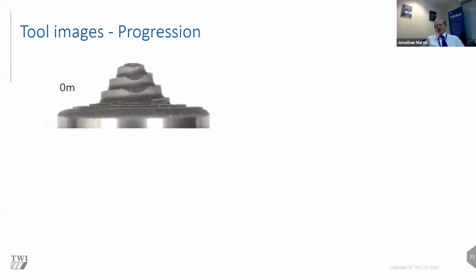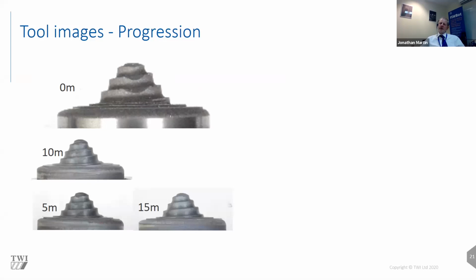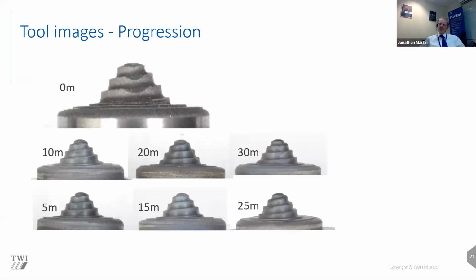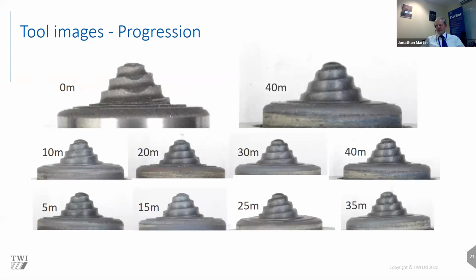So I did mention that every weld, we took a picture of the tool. So this next slide is really showing that progression as the tool built up meters and meters of weld on itself. So this is a picture of a new tool, and these are sequential photographs of the same tool going through after each 5 meter long weld. So you can see here that in essence there is a slight bit of wear, perhaps slightly on some of the crisper edges, just slightly rounded, but in essence, the form, the mixing capability of those tools remained.